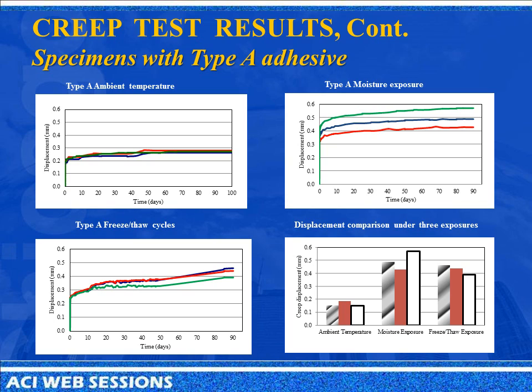So here, when you take a look at those graphs, that's displacement versus time curves for specimens with the type A adhesives. The one on the top left would be the ambient temperature, the one below it would be freeze-thaw cycles, and the top right would be moisture exposure. So you can see the effect when moisture is introduced. You get significant increase in the creep displacement over time and a bit of inconsistency with that product in specific. And again, with the moisture freeze-thaw exposure, increase in creep displacement, but not as inconsistent as the moisture exposure. With the bar chart, you can actually visualize the impact of the different exposures that we get. So at ambient, fairly low, then a significant increase when moisture and freeze-thaw are introduced.